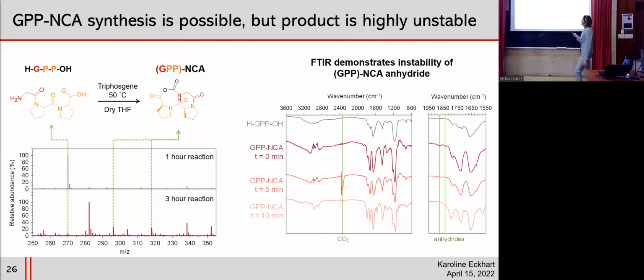In looking at an FTIR of GPP-NCA, we're zoomed in here on the carbonyl region. We can see the presence of anhydride peaks, which represent the anhydride in the macrocycle. And then after sitting on the FTIR crystal for just 5 minutes, we see a reduction in the size of these anhydride peaks and the appearance of a CO2 peak, which corresponds to degradation of the NCA and release of the CO2 from the anhydride. And then after 10 minutes on the crystal, we have no more anhydrides and we're not releasing CO2 anymore.